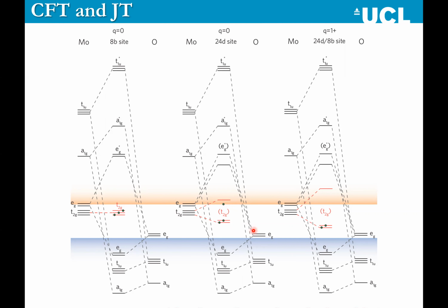But as we know from the EXAFS, the bond lengths are actually shorter than what we found for this neutral charge state. So when you ionize this defect, when this electron has disappeared and is zipping around in the conduction band elsewhere, you get a bond contraction, which of course strengthens the Jahn-Teller distortion, stabilizing these 2 T2g states and destabilizing this unoccupied state, giving you the picture that we saw in our band structures. So this was very interesting. We were able to understand what was happening in the band structures using simple molecular orbital diagrams.